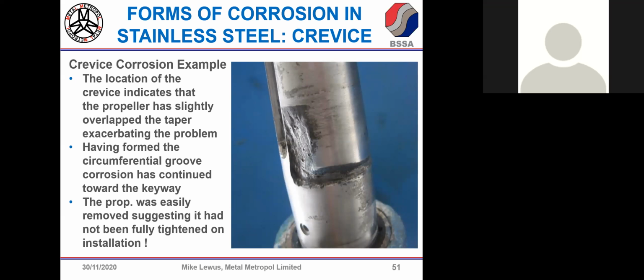This is a crevice caused by poor fitment of a propeller on the prop shaft. You can see the keyway and you can see what's happened for the poorly positioned or wrongly positioned prop. We've got a very deep groove eaten away as a result of crevice corrosion, and it turns a corner and actually the corrosion runs down towards the keyway. So potentially quite serious, because whenever you get corrosion like pit features or crevices, particularly if it's a load-bearing part, those features act as stress raisers. The next thing you'll find is you've got fatigue cracks growing.